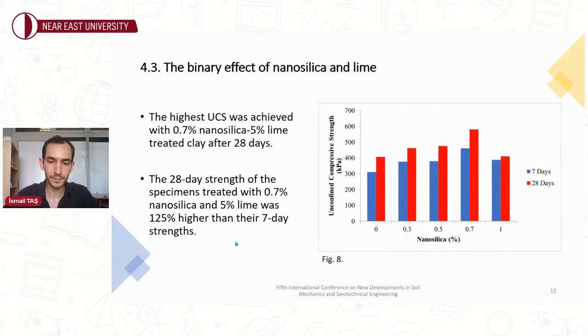The last one, the improvement to be achieved with the combined use of nanosilica and lime was investigated. According to the result of the unconfined compressive strength test, the 28-day strength of the specimens treated with 0.7% nanosilica and 5% lime was 581 kilopascals, and it was the highest strength amount among the experimental groups. The 28-day strength of the same specimen was 1.25 times higher than its 7-day strength.